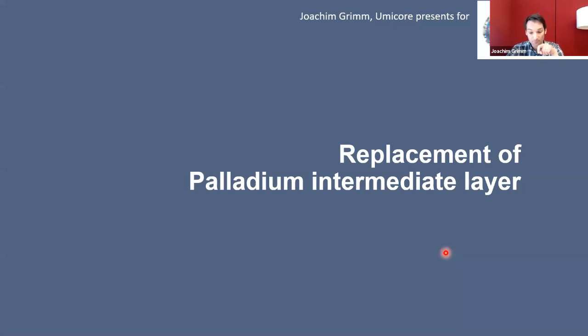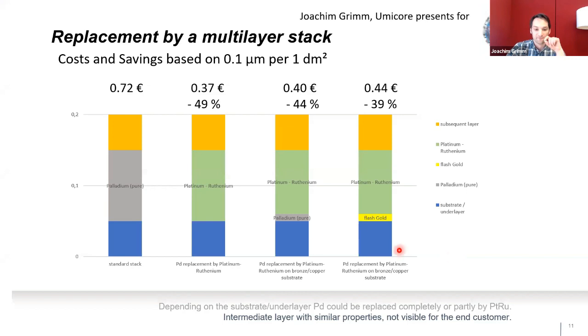So I want to go to an additional point, which is the replacement of the palladium intermediate layer, because if we go straight to sterling silver or silver casted jewelry, it is not just pure rhodium on top. If you see in that column, usually it's the standard stack with sterling silver or silver, and then you do a layer of palladium in between, as palladium gives you a really good migration and corrosion protection. So no copper or other compound of the basic alloy can migrate through the layer or come off on the upper layer on your jewelry. So palladium is a standard intermediate layer on jewelry. If you do the rhodium on top, the calculation you see now is just related to these intermediate layers.